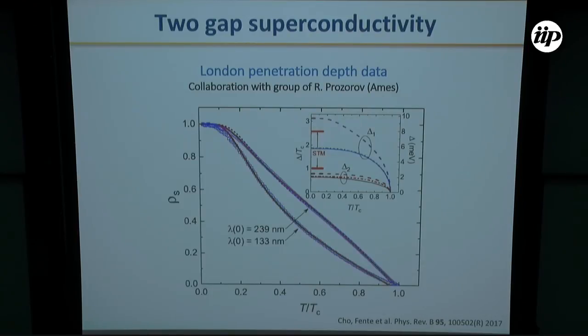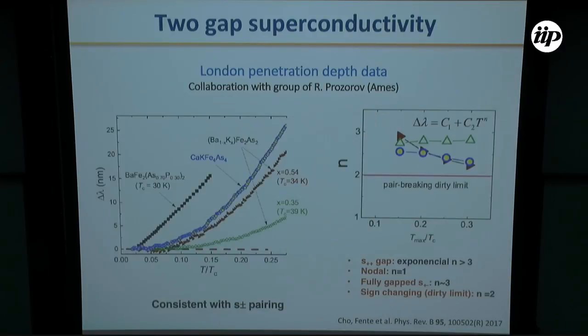We have made a collaboration with the group of Prozorov at Ames. They have measured the magnetic penetration depth on the same samples. And from the temperature dependence of the superfluid density, they also need, to fit their data, the presence of two superconducting gaps with similar values to those obtained with STM. From the low temperature dependence of the London penetration depth, they find that the superconductivity in this material is consistent with S plus minus pairing.